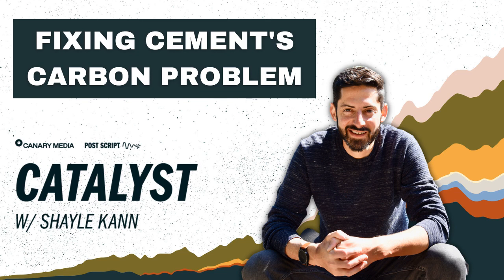So folks add extra silicates to the cement, and that soaks up the extra calcium, and that improves the durability, improves the density, and also improves the performance in many ways. So there are a number of different sources of silicates. Right now, fly ash is very popular. So fly ash is an amorphous silicate collected from coal-fired power plants. And of course, those are going away, and for a good reason. But it does mean that there's a shortage of fly ash, a near-term shortage.